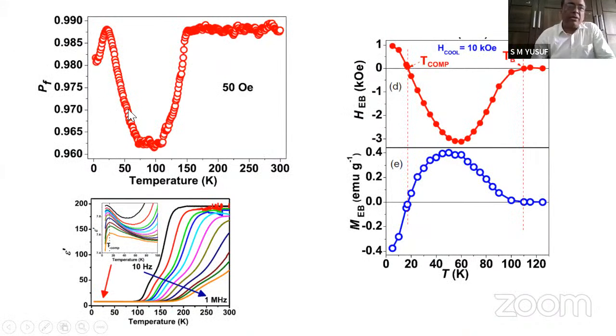Now, again here we show the polarized neutron study, as I showed for the other cases. We do see recovery of the neutron beam polarization fully at this point, and maximum neutron depolarization where you have maximum magnetization. But interestingly, we see the exchange bias, and you see the exchange bias both with regard to the field axis and with regard to the magnetization axis. And there is a polarity reversal of exchange bias at this compensation temperature, both in the field axis and the magnetization axis.